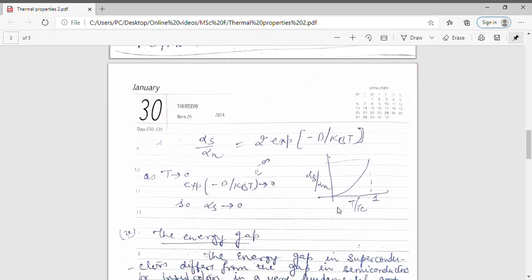The variation of alpha s upon alpha n, the ratio of the two attenuation coefficients, with temperature, I have plotted on the graph with T upon Tc on the x-axis. T upon Tc equal to 1 means this is the critical temperature. The variation shows a curve which is continuously increasing as temperature increases from 0 to Tc.